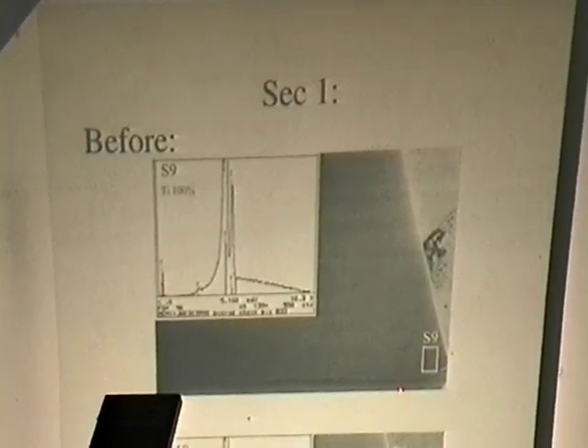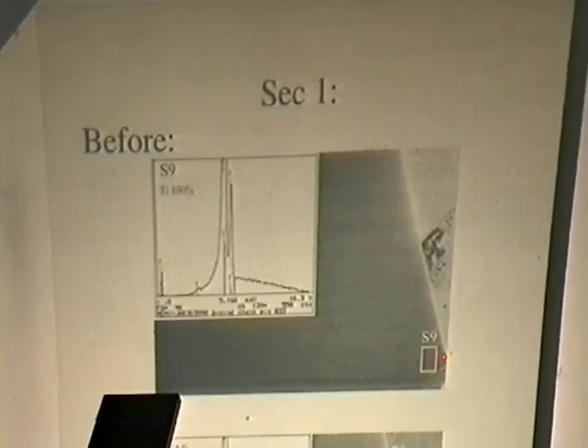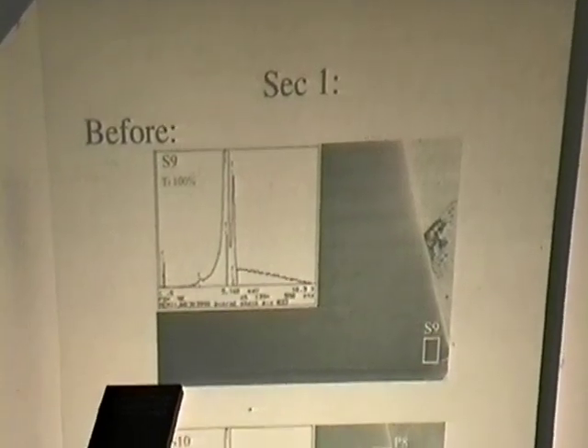The spectra I took with an EDS, Energy Dispersive Spectrometer. I took here and here. This is before and after. Before, we had 100% titanium. Afterwards, we had 100% titanium and a trace of sulfur.